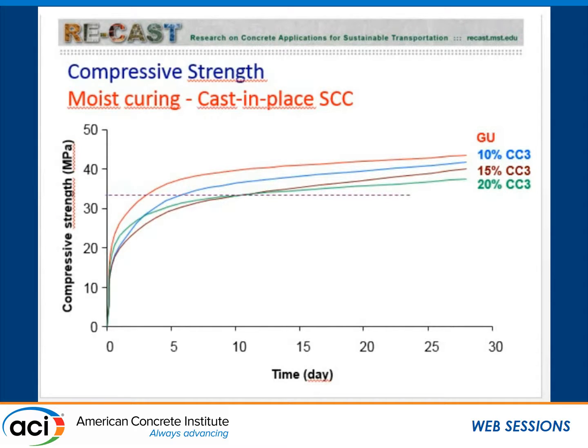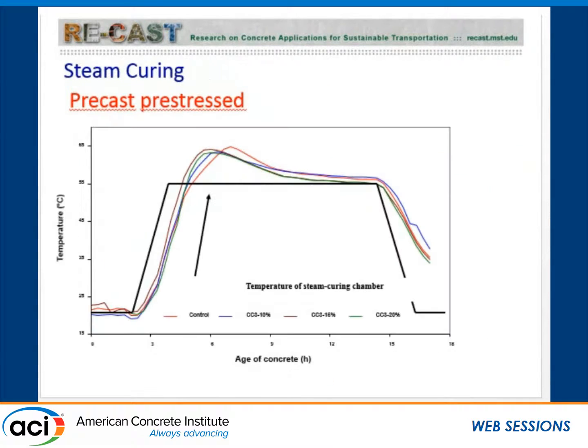And in this case, the target was getting 32 MPa at 28 days. And again, it was mix design. If you know this, you can anticipate it and compensate for it. For the pre-stressed application, we had a pre-stressing chamber. So this is the regime that you use for the steam curing chamber, and these are the temperatures inside the cylinders. Again, you follow the same regime.